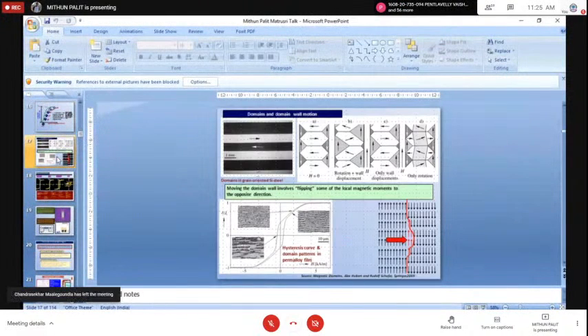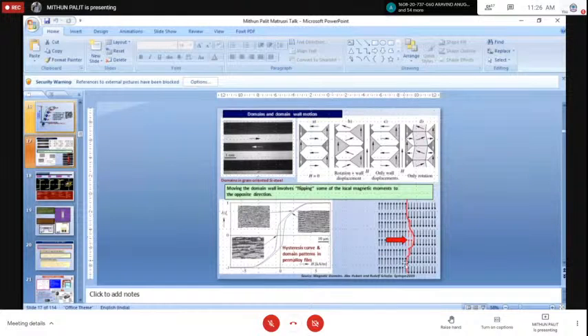Well, as I was saying about the magnetic domain, let us see how they actually look. You can see in a grain oriented silicon steel the configuration of the magnetic domains. The color contrast tells us that the two domains are in two opposite directions. And as I was saying about the domain movement mechanism, you can see this cartoon over here, the bottom one. So what happens is that whenever, the first thing of course is rotation.